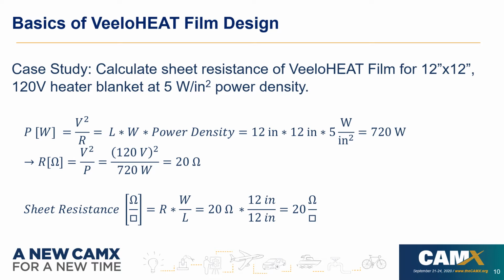And then for sheet resistance, that is going to be resistance times width divided by length. Because this is a square in this case study, we ended up with 20 ohms per square sheet resistance target for this electrothermal film. So once we have that number, we would send that off internally, release that design, and then we would manufacture that film for this product.